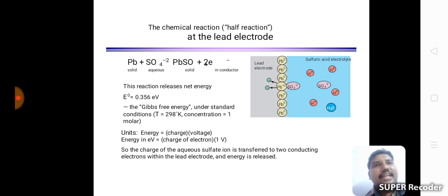The chemical reaction at the lead electrode: Pb plus SO4 minus 2 gives PbSO4 plus 2 electrons. This reaction releases net energy E0 equal to 0.356 electron volts, the Gibbs free energy, under the conditions T equals 298 Kelvin and concentration 1 molarity, with energy equal to charge times voltage, in electron volts. The charge of the aqueous sulfate ion is transferred to 2 conducting electrons within the lead electrode and energy is released. This is the energy reaction at the lead electrode.